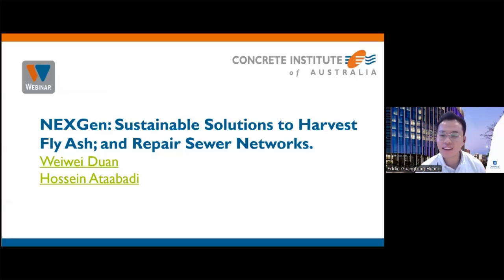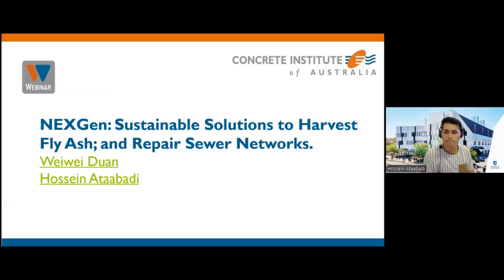Another question from Liam Martin from UTS, for Hossein. Can the capsule be varied in size, and does this affect the workability of the mix? And is it comparable to fly ash or other SCM materials? Yeah, actually the capsules I produce in my project currently are between 4 to 7 millimeters, like a coarse aggregate for now. I've included them in the mixes at 2%, 4% and 8% replacement. Increasing the percentage definitely reduces the workability, and it also reduces the strength, because there is lots of pore structure in the capsule once we add it at higher replacement rates.